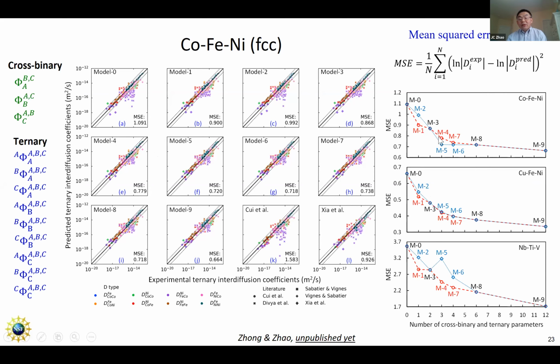You can see now the error is much less. When you start adding more and more parameters, it doesn't give us anything, right? If 12 parameters, compared to 4 parameters, it's very little improvement. So our suggestion is not to use more than 4 parameters. This is the 3 parameter model, that's M4, the three independent cross-binary terms, and that's how the system works pretty well in that case.